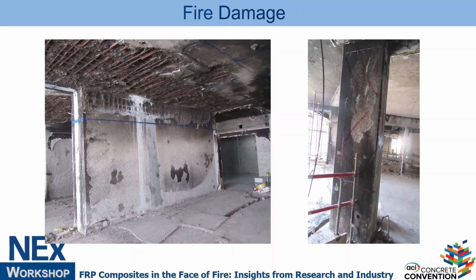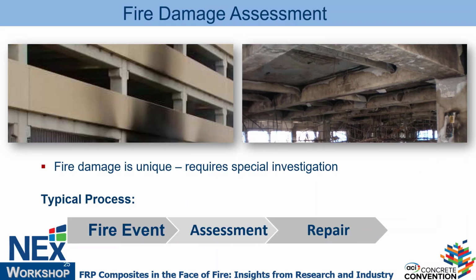And I mentioned that because this relates to something we do with FRP. With FRP, if we want to do fire protection on the underside, we can easily apply spray material or boards or something like that. On the top side, it's not easy to fire protect FRP, because fire protection typically is a soft material, which doesn't make sense to apply on the top side, plus there's a change in elevations. So I've seen many cases in which building officials, based on the statements in 216 and general knowledge about fire, accept that fire protection be limited to the underside, not required for the top side. Of course, it's different from building official to building official, but you can see that's getting more acceptance now.